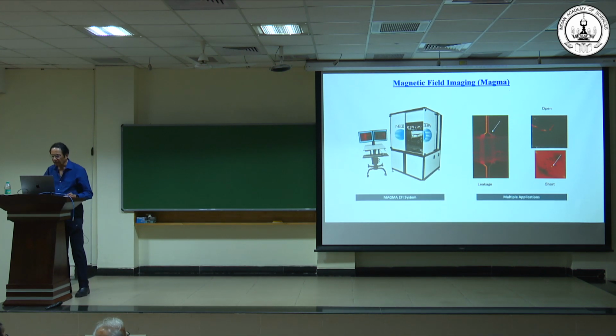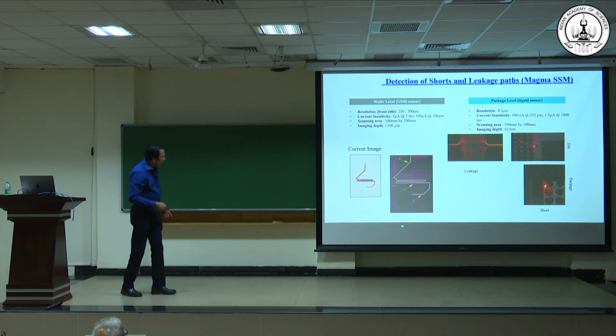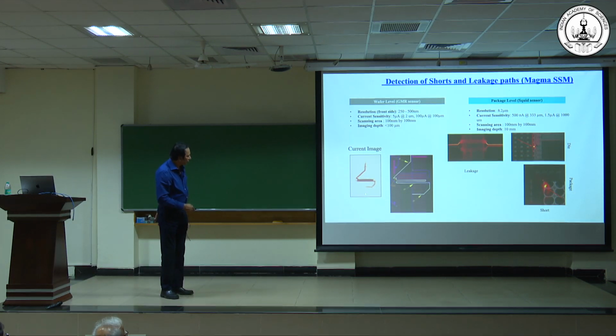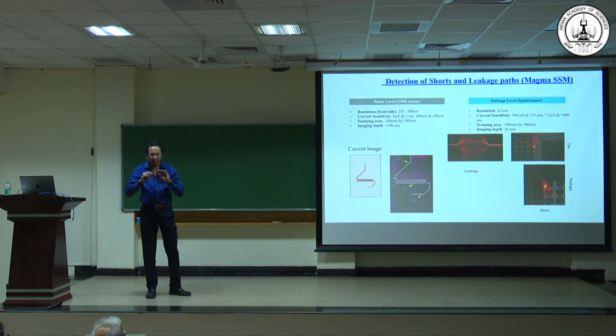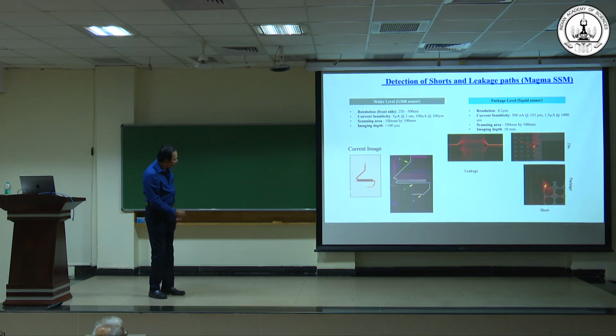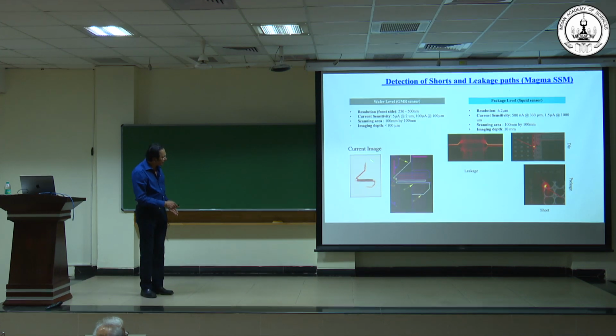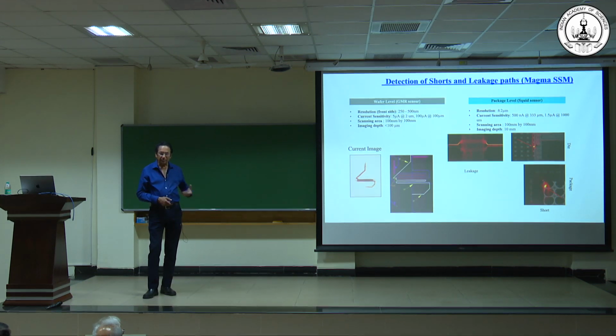I'll give you one interesting example here. This is a multi-chip module. This is a chip which has 4 layers which are separated by 40 microns. The current is coming from the bottommost layer, and it comes up, then comes to the topmost level which is closest to the detector, then goes back to the next level and then the lower level. So you can see there's a lot of information on depth here, right? If you're far away from the detector, the information gets fuzzier and also weaker. So actually we can use this to measure Z.